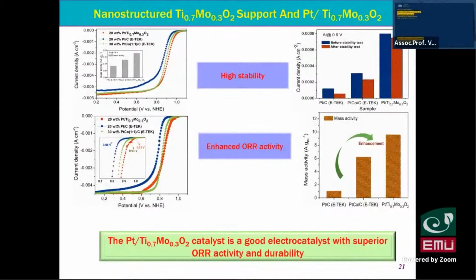After that we measured the electrical property compared to the commercial catalyst, Pt on carbon, and second, Pt-cobalt alloy on carbon. Our result, shown in red, shows the activity becomes higher than the commercial catalyst, and we also checked the stability test, which shows very high stability. That means we can enhance the stability of the fuel cell system using the new material compared to the commercial catalyst, Pt on carbon support.